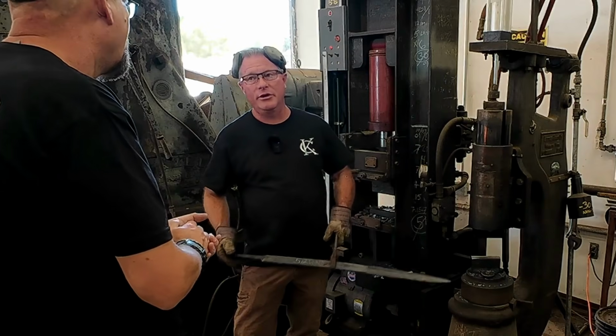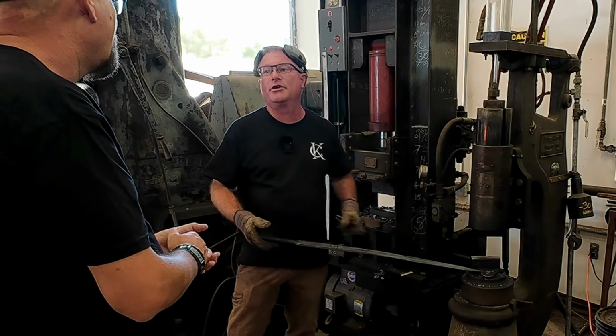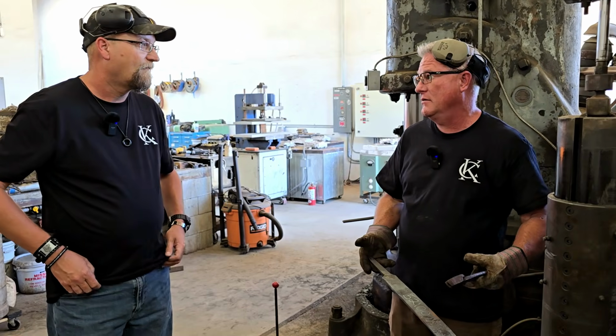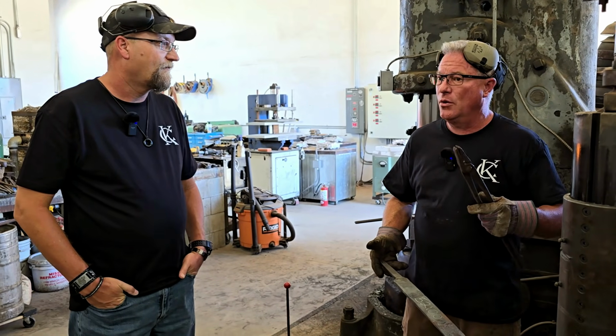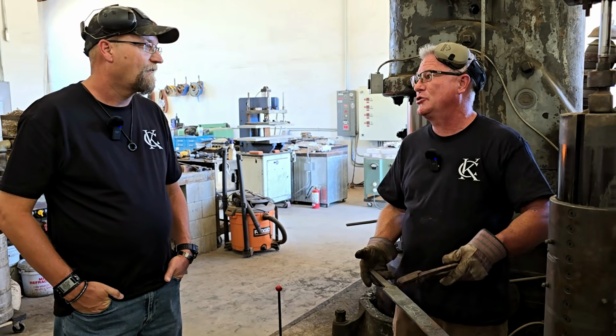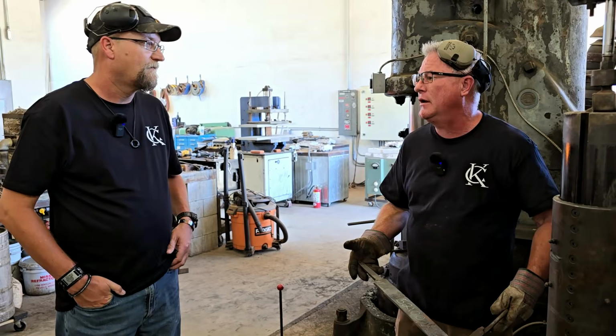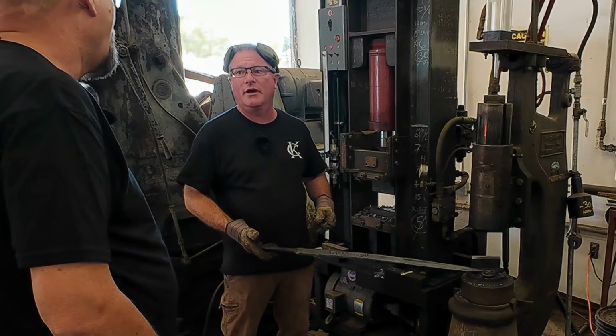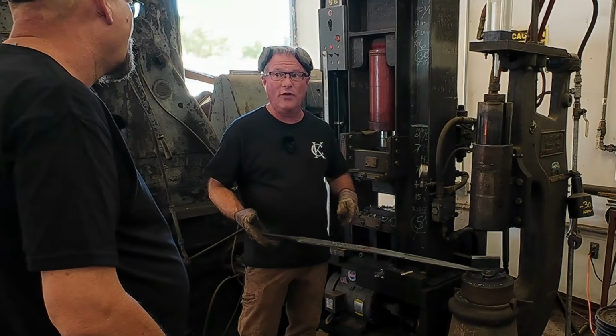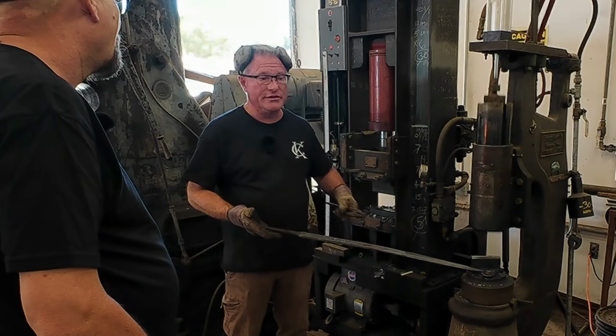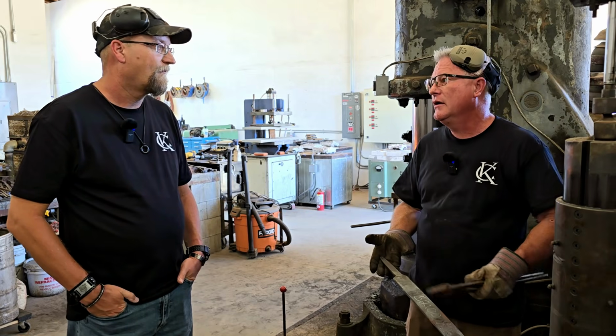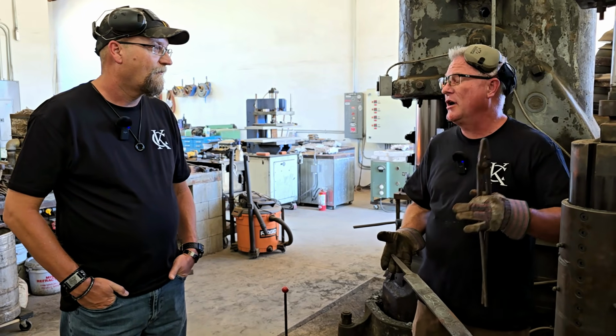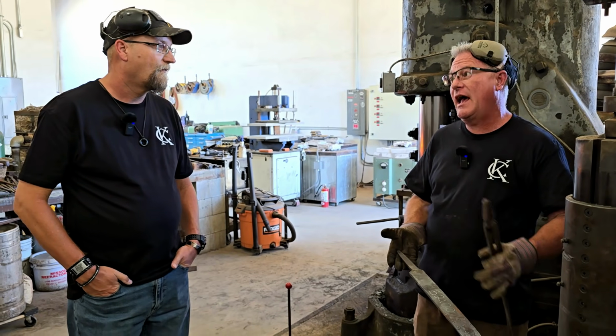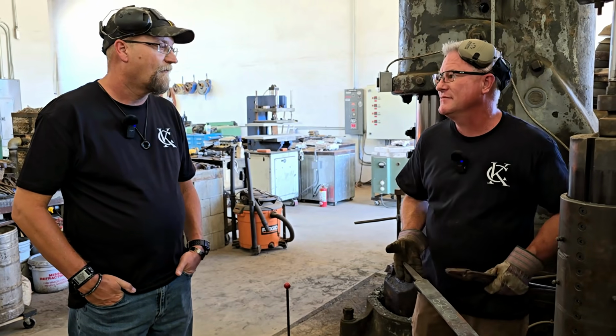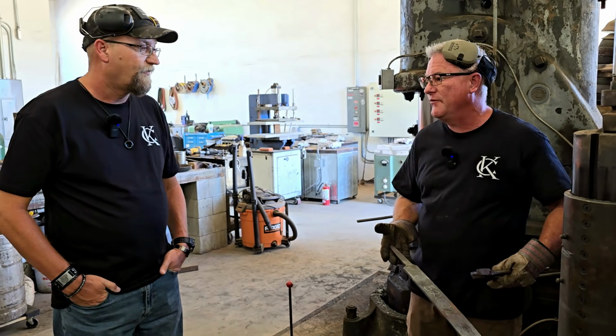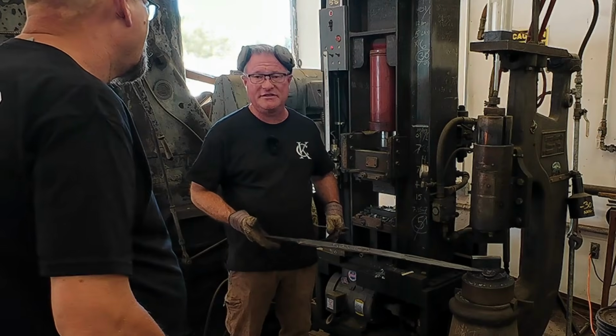What happens next? Then it's going to go through different thermal cycling. It's going to go through a heat treating process to soften it and to align the grain structure. That can involve a lot of time at temperature in a kiln, and slow cooling, because you want it preferably buttery soft. A lot of blades, I will heat treat them rough forged and then grind, but they all get thermal cycling. At least in this shop, it's done with digitally controlled heat, exact times, temperatures. It's not done in the forge, especially with the alloys I use. They're not very adaptable to that. They're more temperamental. Yeah, they need very specific times and temperatures.